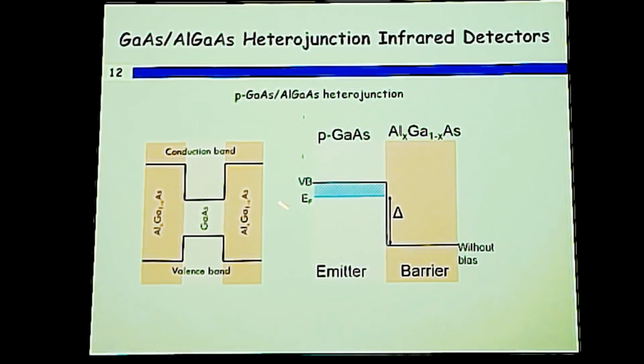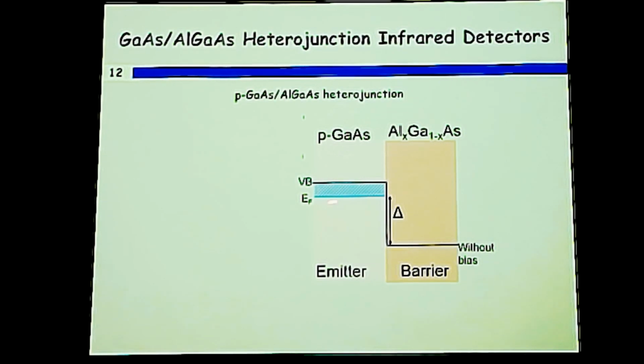This is a typical heterostructure band alignment: gallium arsenide, low energy band gap; aluminum gallium arsenide, high energy band gap. And we can change this offset by changing the aluminum fraction. So for the p-type, highly doped, close to 10^19 per cubic centimeter or so, the Fermi level is in the valence band, and the difference between the Fermi level and the barrier controls the energy gap, and that controls the spectral photoresponse wavelength. And for the operation, we apply bias, and if there is incoming infrared radiation of certain suitable energy, then that can be detected. It can also be operated without bias if the barrier is graded by changing the aluminum fraction from a low value of x here to a high value of x here. This can also operate at zero bias.